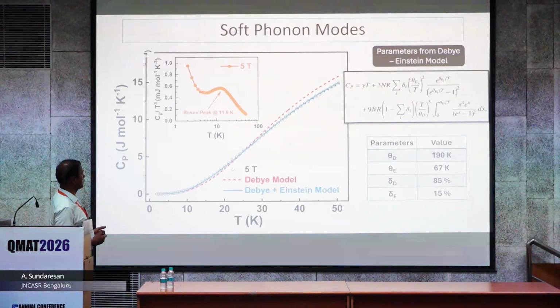Another aspect we see in this is the heat capacity phonon part, fitting the Debye and Einstein model, which fits very well. There's about 15% Einstein contribution and 85% coming from the Debye contribution. We try to fit the parameters obtained here, theta D and theta E are given, and you can see theta E is lower than theta D.